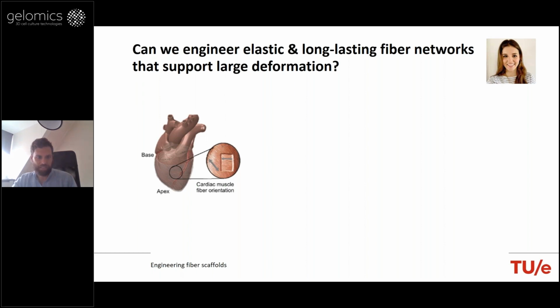So one of the candidates that we came across was silk for the known mechanical properties that are widely described in the literature. So silk is extremely strong and elastic, and then of course would provide an alternative to thermoplastic materials, in this case PCL. But one of the limitations when we process silk, or in this case when we extract silk, is that we destroy the structure of silk. In this case, basically the beta sheet structure and the molecular alignment of the silk molecules, which basically then imparts the elastic performance